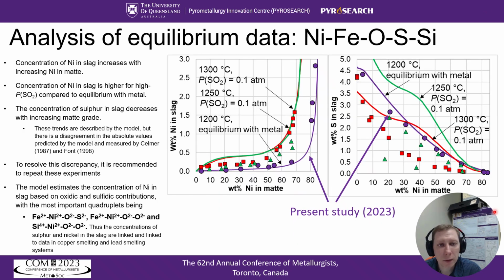Now, we can analyze the results for the same equilibria conditions in terms of slag composition. A very important parameter is the true chemical solubility of nickel in slag. It increases with increasing concentration of nickel in matte. Both experimental data and thermodynamic model predictions indicate that slags at high PSO2 conditions dissolve more nickel compared to the case in equilibrium with metal.